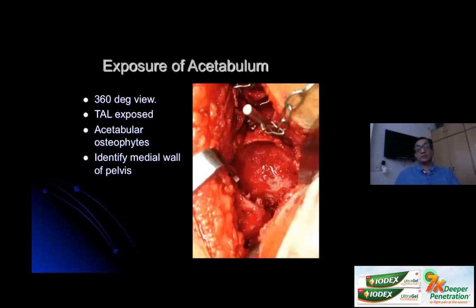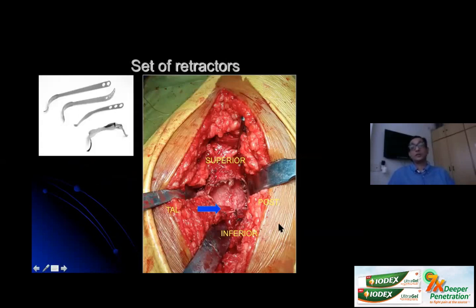The next step is to get the technique right. The first step in achieving that good technique is to have a very good exposure of the acetabulum. We should be able to see the acetabulum all around, 360 degrees view is very important. You need to see and identify the TAL, the osteophytes need to be seen, and you also need to visualize the medial wall of the pelvis properly so that you can insert your cup and do the cementing very well. Again, a new set of retractors do go a long way in achieving that. Here you can see the cup all around, all the 360 degrees of the cup can be seen nicely. You can visualize the TAL properly, and that is the first step.